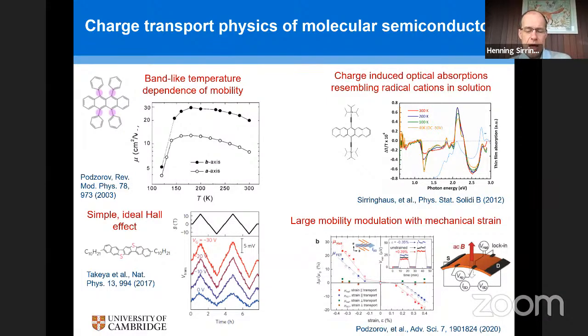So that also is a very clean semiconducting transport. But then there are also other aspects of the physics of transport that are a little bit more peculiar. We have worked in our group a lot on the optics of charges in these materials. So if you induce carriers into an organic semiconductor and look at what optical absorption these charge carriers have, what you typically see is a very characteristic sub-band gap absorptions in the infrared that are characteristic for these charge carriers.